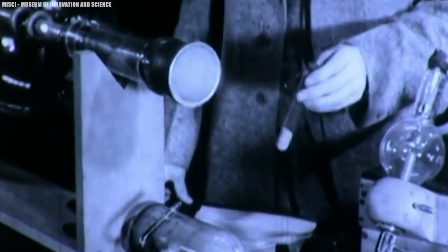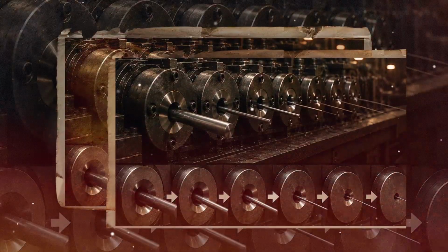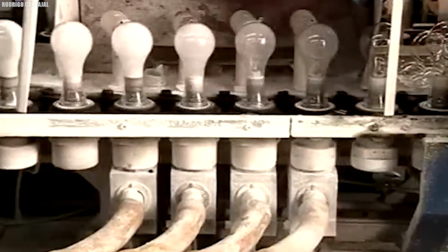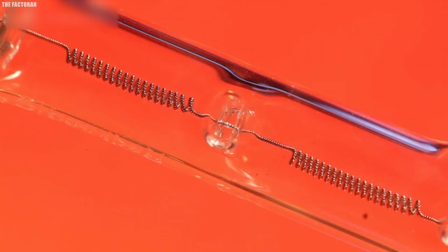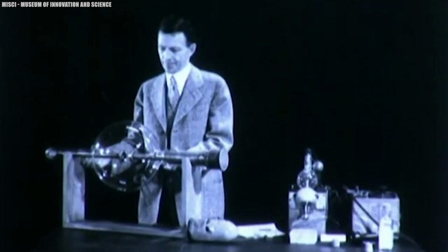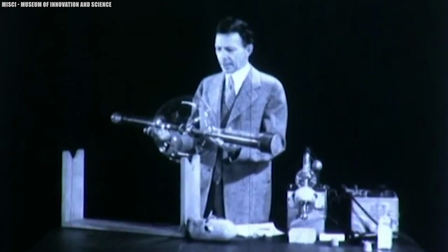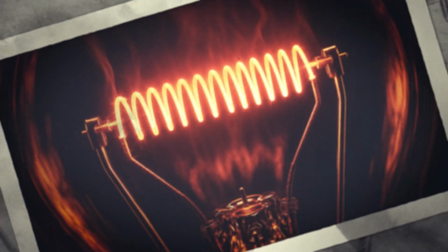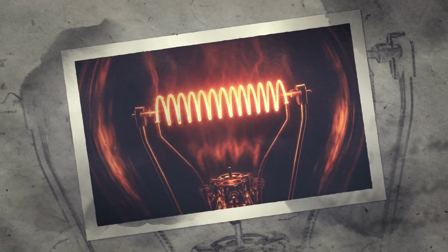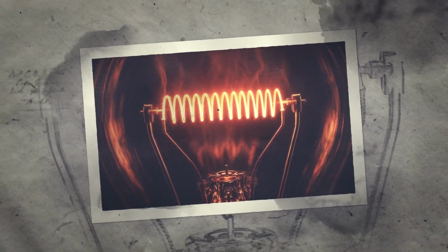Following mechanical working, the rod was drawn through a series of progressively smaller tungsten carbide dies, each pass reducing its diameter incrementally until wire finer than a human hair emerged. Thin enough to be nearly invisible against a white background, yet capable of operating continuously at temperatures exceeding 2,500 degrees Celsius during lamp operation. Once the wire reached its final specification, it moved directly to the winding stage.